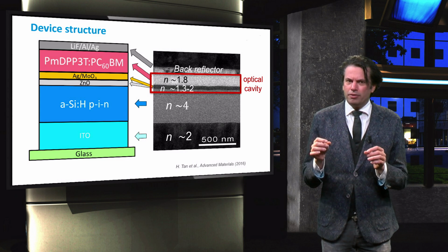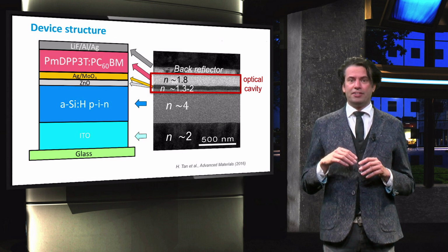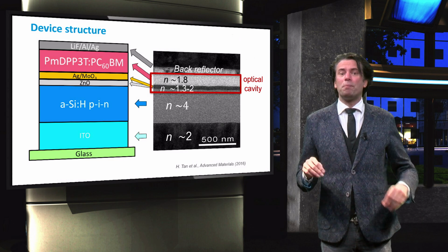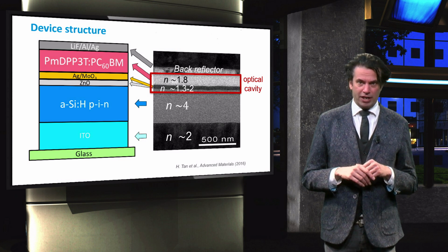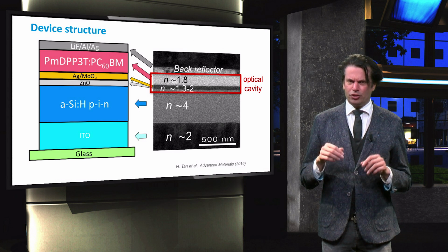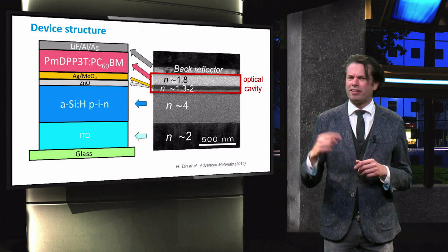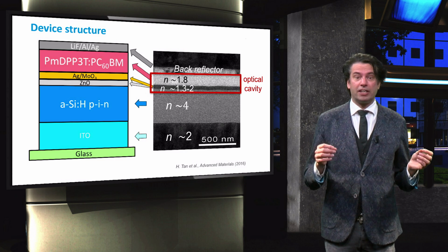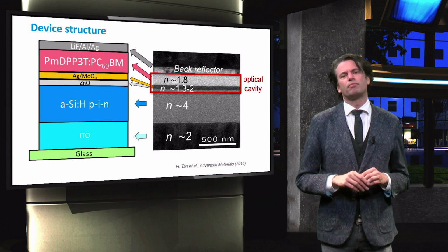The organic material, the molybdenum oxide and the zinc oxide layers have a significantly lower refractive index in reference to the back reflector and the silicon top cell. This means that an optical cavity is created in this relatively flat thin film device. It will optically operate in the diffractive regime. The absorption of the bottom cell depends on the interference effects and is determined by the thickness of the optical cavity, the refractive index of the optical cavity, the refractive index mismatch with surrounding media, and the wavelength.